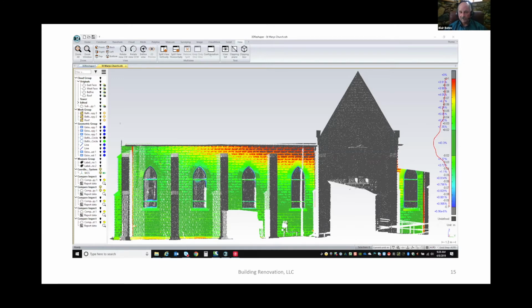All these cracks throughout the building, they just wanted them caulked and repainted. And they've done everything to kill this building. This is a cement block. When the block started to deteriorate, they used a latex modified cement slurry and painted the whole building with it. They continued to deteriorate, so then they put paint on the building. It continued to deteriorate by all of these cracks. So now they sprayed it with a silicone sealer. Why, I have no idea what they were thinking, trying to get these cracks fixed. So now nothing will stick to the outside of this building without major efforts.